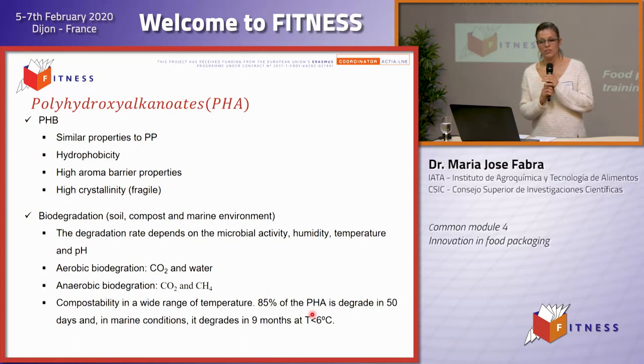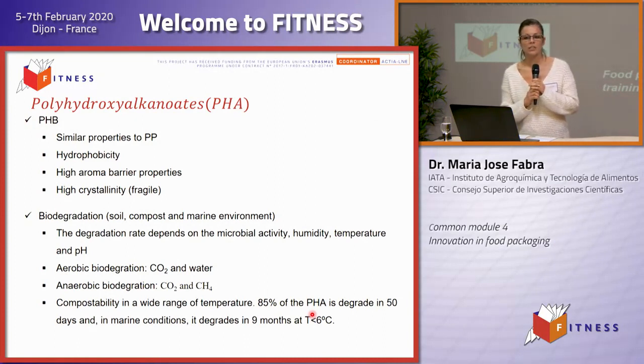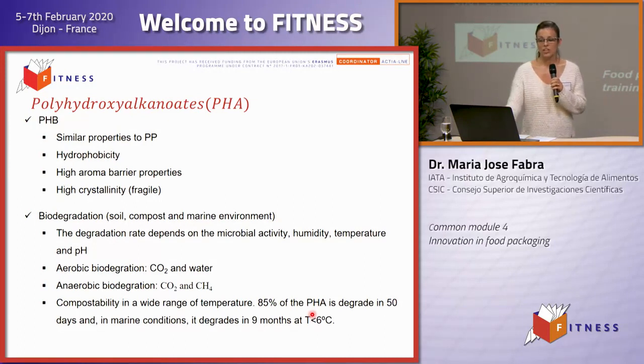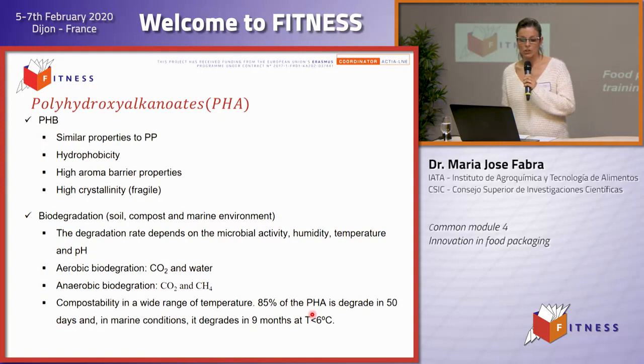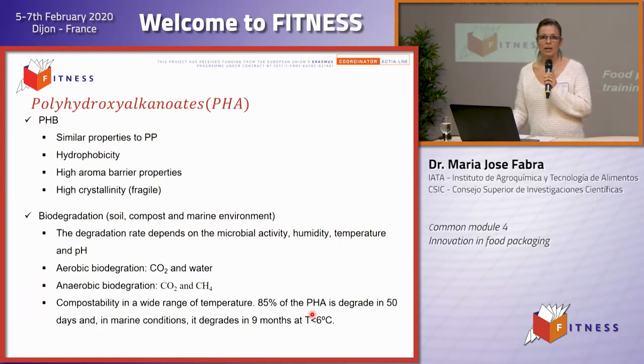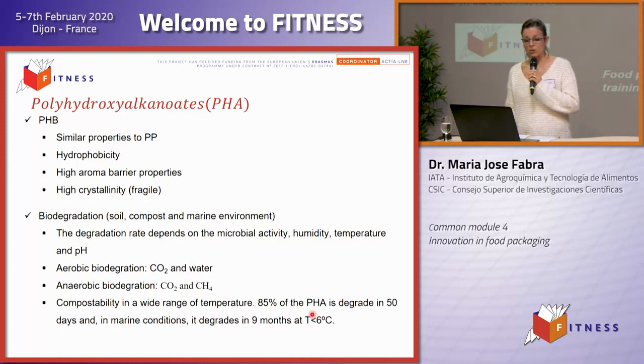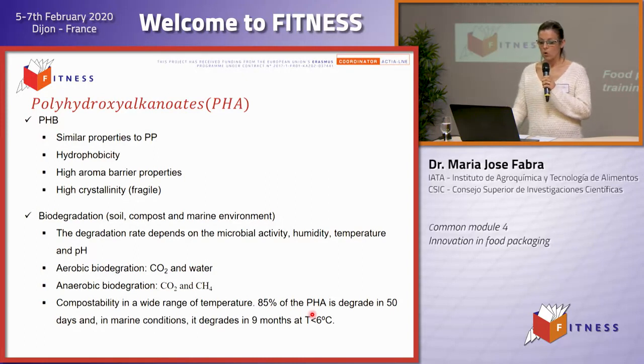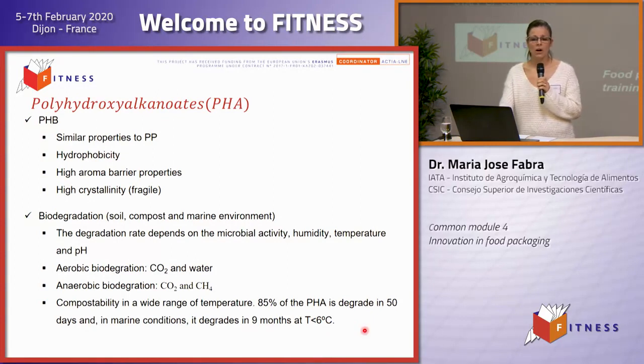One of the most common PHA materials is polyhydroxybutyrate, PHB, which has similar properties to polypropylene. It's more hydrophobic than starch and PLA. It has high aroma barrier properties, but it is fragile, and it has high crystallinity. PHB can be degraded. The degradation rate depends on the microbial activity, humidity, temperature, and pH, and it can be degraded in aerobic and also in anaerobic conditions. It is compostable in a wide range of temperatures. 85% of the PHA degrades in 50 days, and in marine conditions, it degrades in 9 months at temperatures lower than 6 degrees.